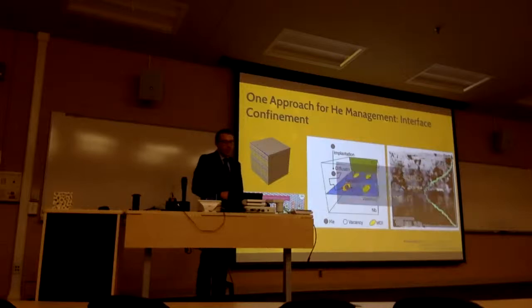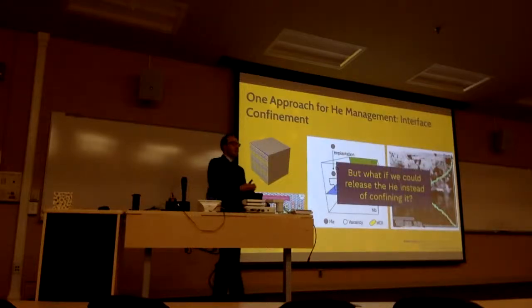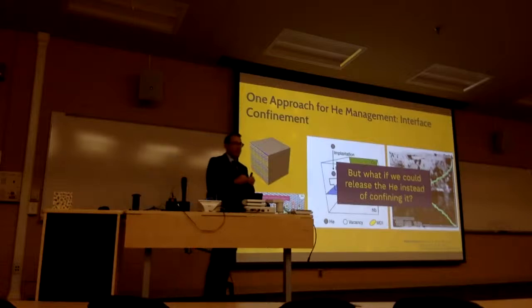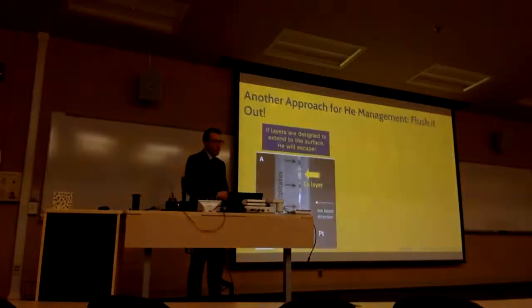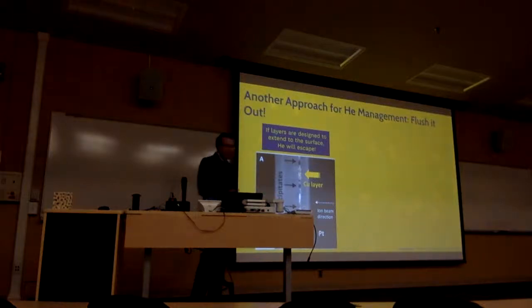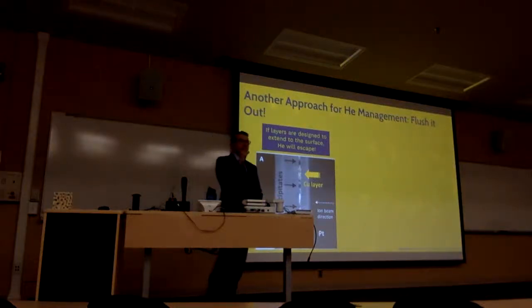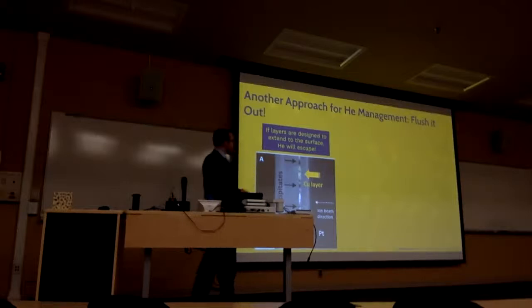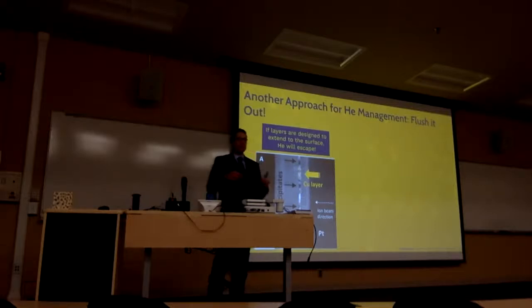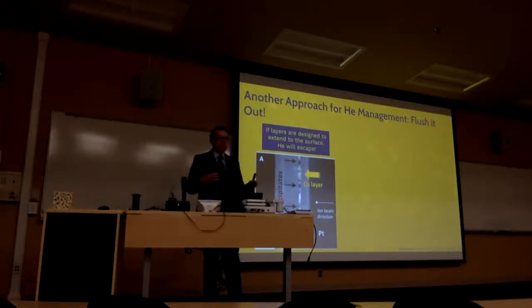But what if, instead of confining the helium at the interface, we could flush it out during irradiation? What if we could just let it escape outside the surface? That would put an upper limit to how embrittled the material can become. Recent studies actually concluded that if you can design interfaces very specifically, you could develop nanochannels of helium bubbles at an interface, and if those interfaces extend to the surface of the material, that helium could be flushed out at the surface.